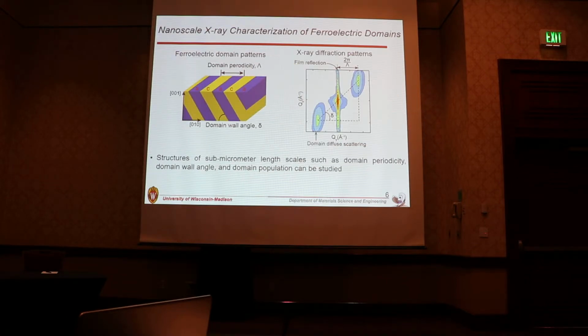Periodic domain patterns give rise to satellite peaks called domain diffuse scattering around the barium titanate reflections in our case. So as you can see here, domain diffuse scattering forms around these barium titanate reflections. It's just a schematic, not the data. By using the domain diffuse scattering positions and its intensity, we can study the domain wall angles, the periodicity, and also the population of the domain patterns in the system.